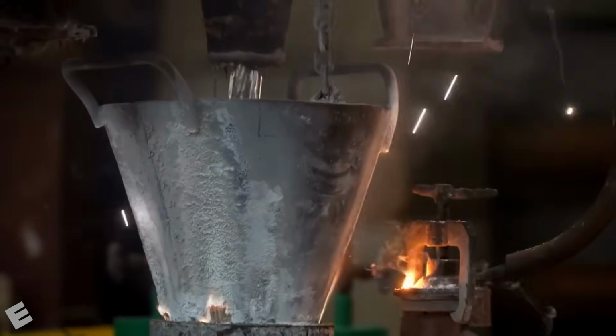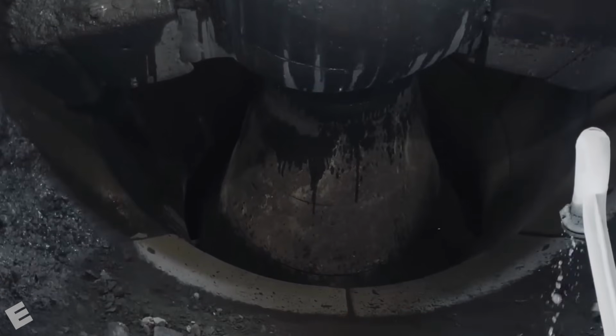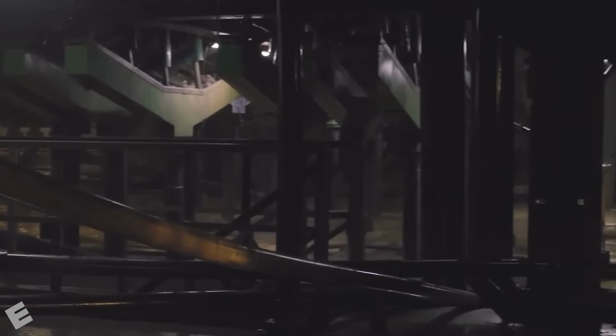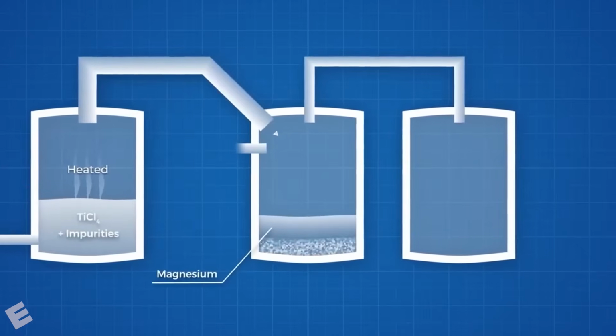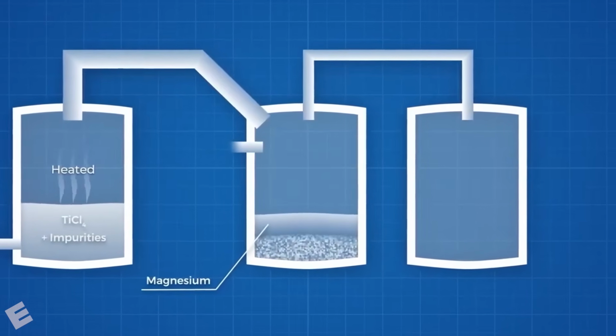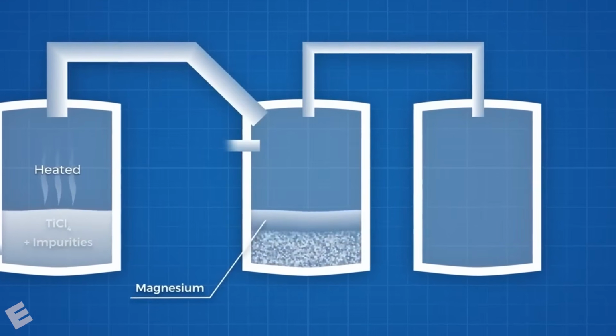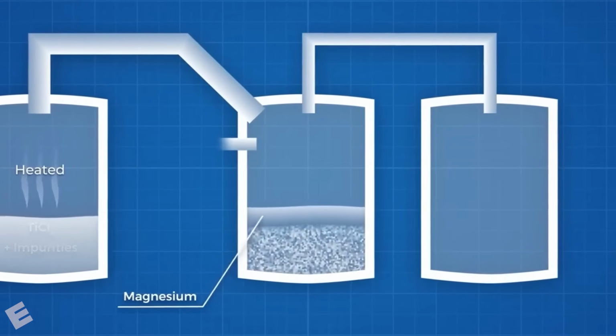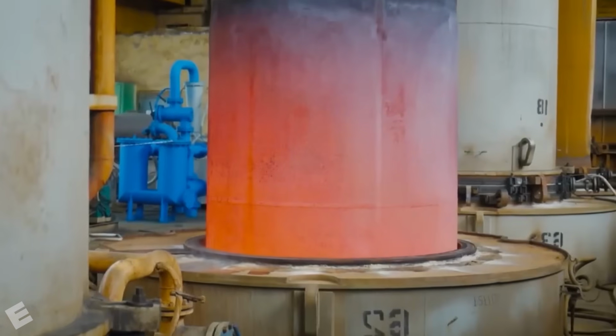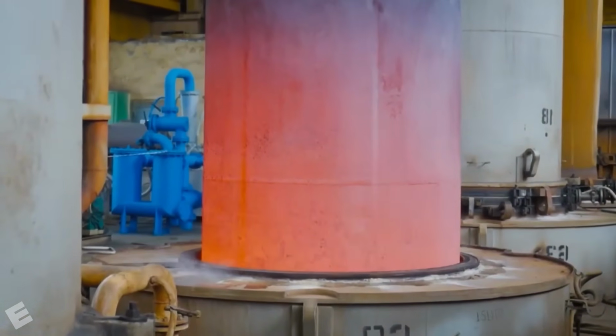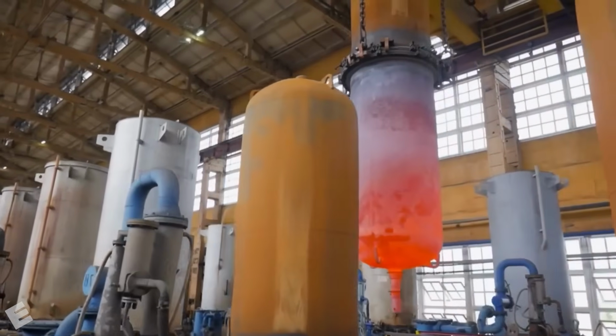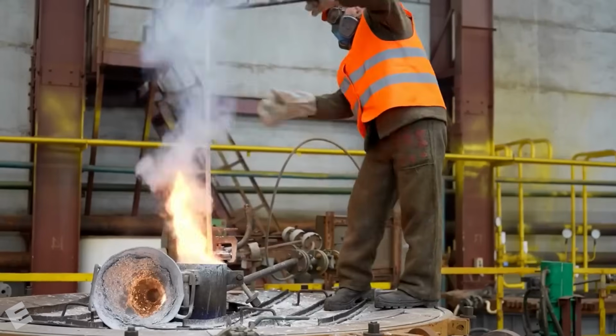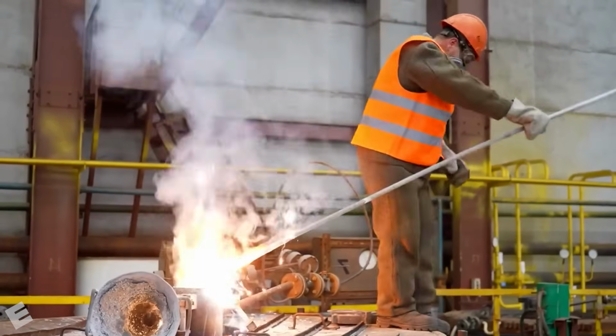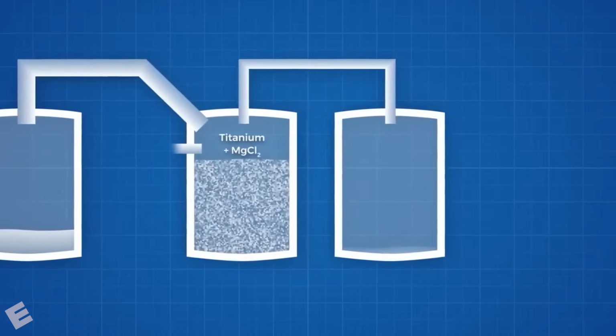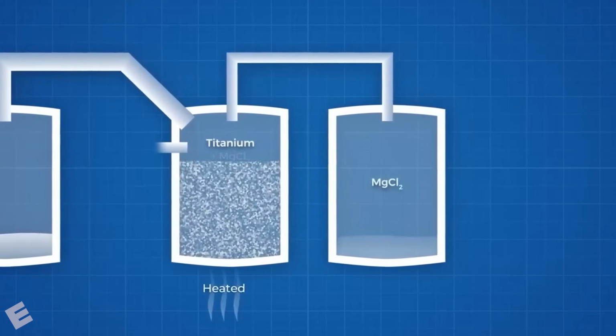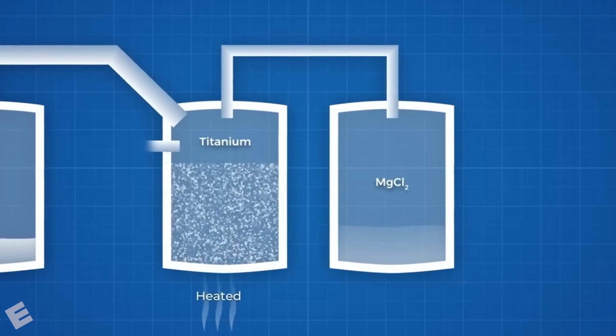The next challenge is recovering the titanium by separating it from the chlorine. This is where one of the most expensive stages begins. Another valuable metal, magnesium, must be introduced into the process. Titanium tetrachloride and magnesium are placed inside large, sealed reactors and heated to between approximately 1,470 and 1,650 degrees Fahrenheit for several days. During this period, an important chemical reaction takes place. The chlorine bonds with the magnesium to produce magnesium chloride, while the titanium is released in solid form.